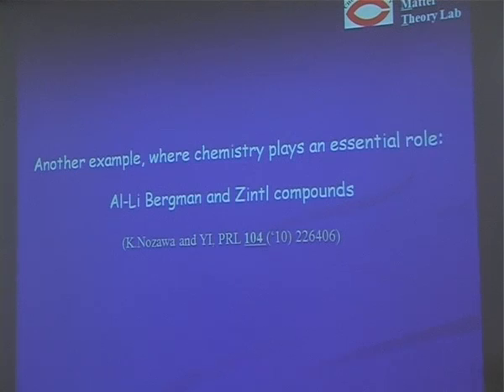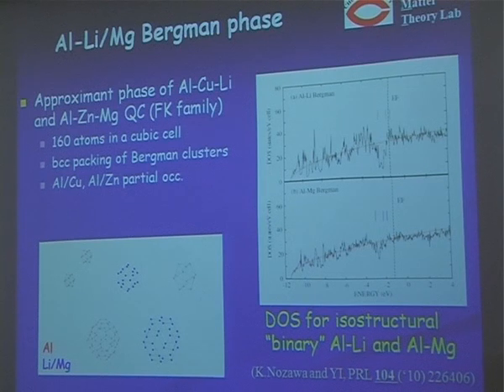In the rest of my talk, I would like to show you another example where chemistry plays an important role. That is the aluminum-lithium Bergman and Zintl compounds. The Bergman phase is an approximant phase of aluminum-copper-lithium and aluminum-zinc-magnesium quasicrystals. And this one has 160 atoms in a cubic cell, and the structure consists of the BCC packing of so-called Bergman clusters. And actually we have some partial occupancy of aluminum-copper and aluminum-zinc in this system. But in this calculation, we assume that this partial site is only occupied by aluminum.